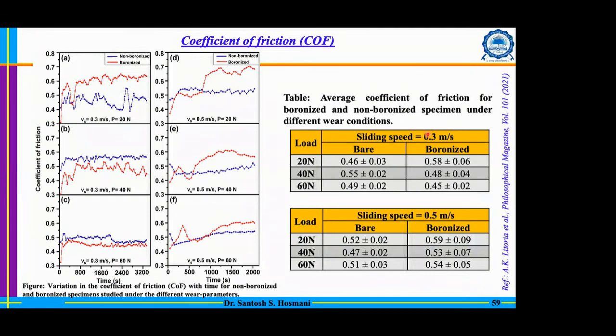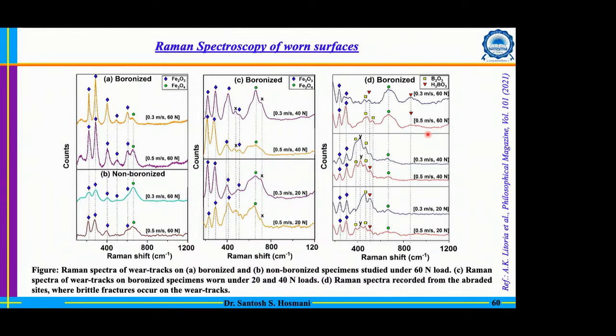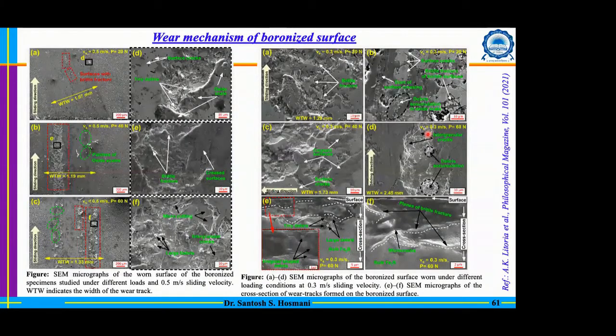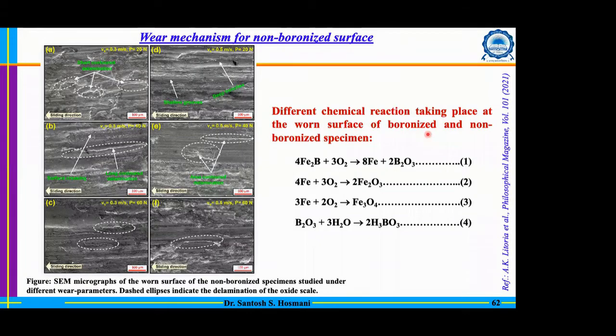Okay. So now, as I mentioned, the coefficient of friction is still very high, 0.4 to 0.5. So it's not really good. And this wear mechanism we studied, and mostly the wear is cracking and oxidation. These two phenomena are actually dominating, and that is causing the loss of material generally. During sliding, there is oxidation of the surface, and that oxidation debris is actually causing the further wear of the boronized surface.